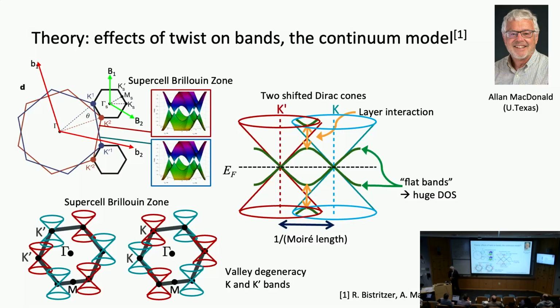And this was a key point in realization, because the flat bands create their own density of states. Here's again a diagram of the energy on the vertical axis and the density of states on the horizontal, and the flat bands create this density of states. Compared to graphene density of states, you would have to multiply the graphene density of states by a factor of 1,000 to make it visible on the same scale. In other words, you have enhanced the density of states due to the presence of the flat bands by roughly a factor of 1,000.